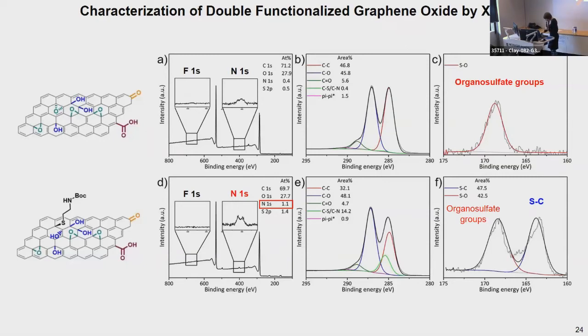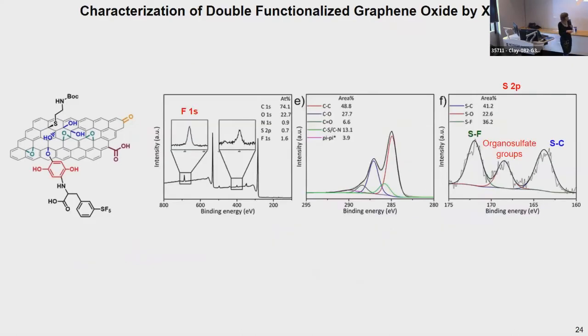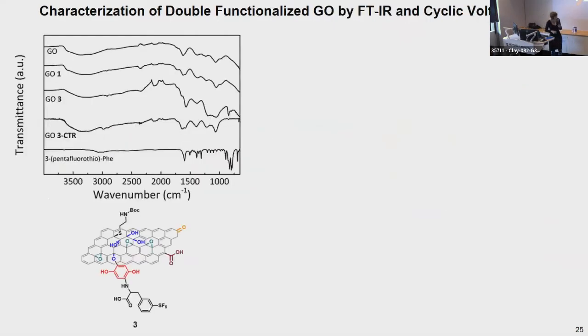And most importantly, looking at the XPS of the final conjugate, there was the appearance of the F1S peak thanks to the SF5 moiety here. And in the S2P area, a third peak appeared assigned to the S-F bond. So again, confirming the presence of this functional group on the surface of graphene oxide. So you see that XPS allowed us to confirm the occurrence of the two successive reactions.